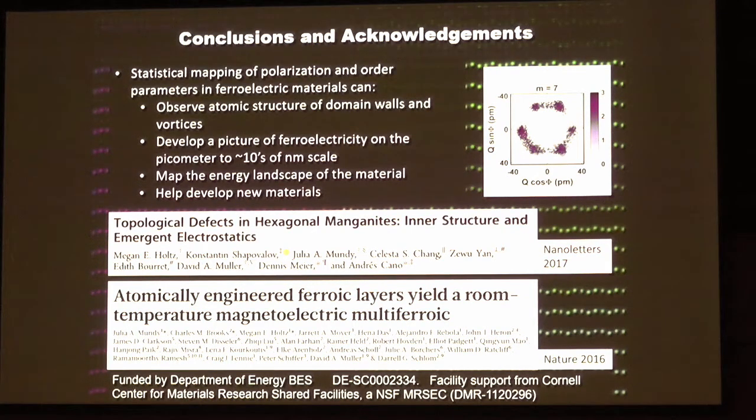Do the charge domain walls make it difficult to switch? So we were hoping that the charge domain walls would be the conduction pathway because the bulk of the material is insulating. So ideally, if you're going to make a charged ferroelectric domain wall device, you would be able to control the placement of those walls and then use single walls to switch. No, I meant to switch the whole material. Oh, yeah. So are you talking about the superlattices or the bulk crystal? But just in general. Yeah, so when you switch them, the walls which are of the polarization which is not preferred shrink down. And they're topologically protected, so they're still there. And then whenever you switch the other way, this relative size changes.